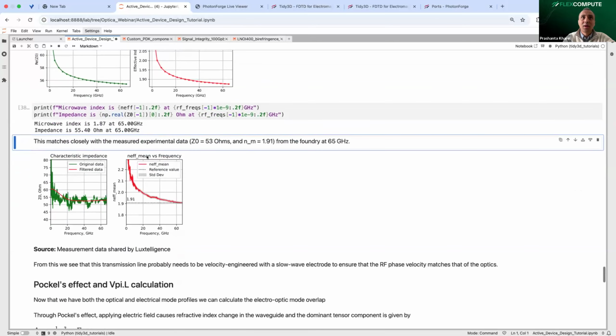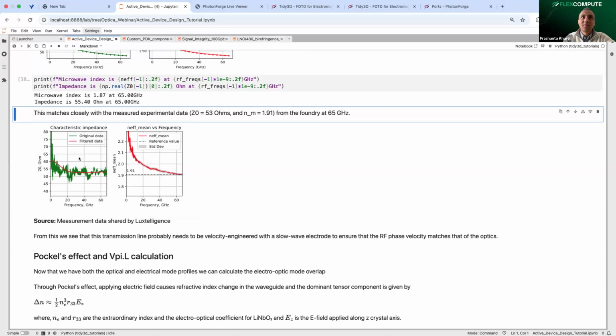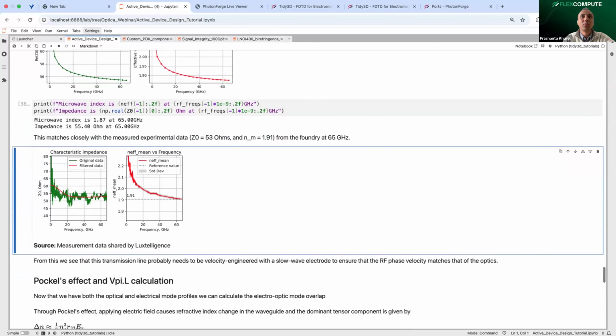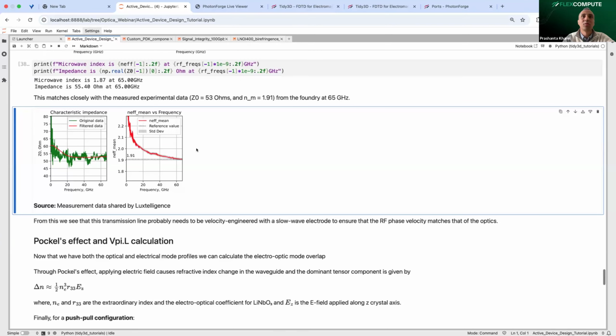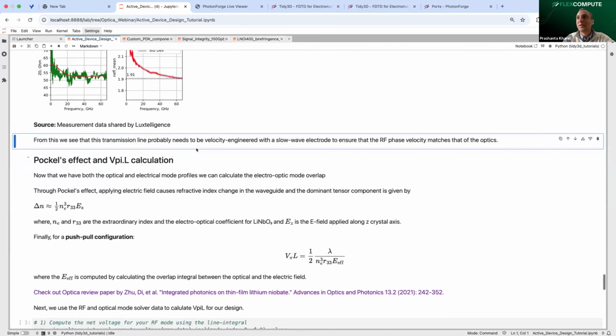Now, this is measured data from Luxtelligence, and we're very grateful that they provided us this measurement data. We see that what we simulated matches very closely with what they measured, and the error in the microwave index is less than 2%, and the error in the impedance is less than 5%. So these are really good results.